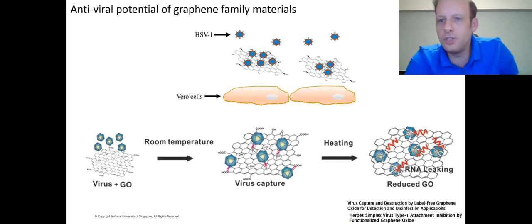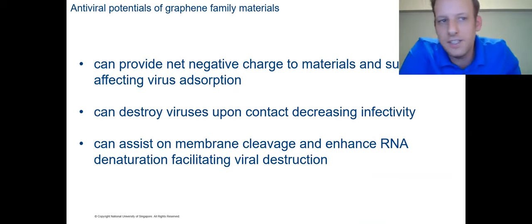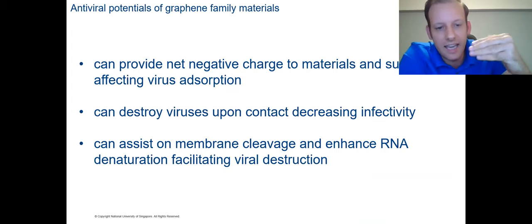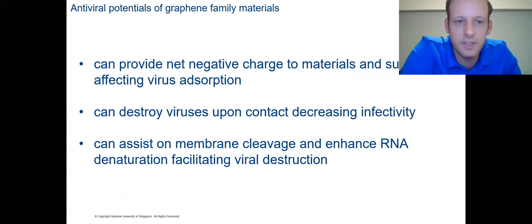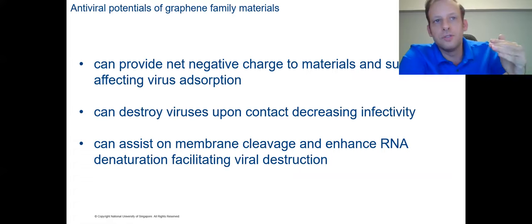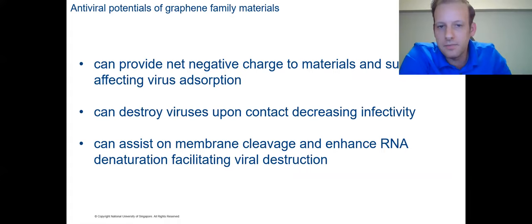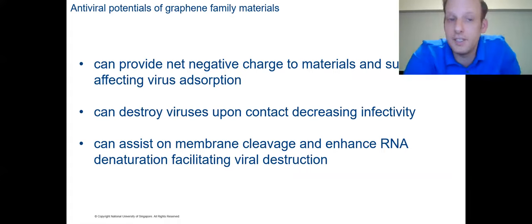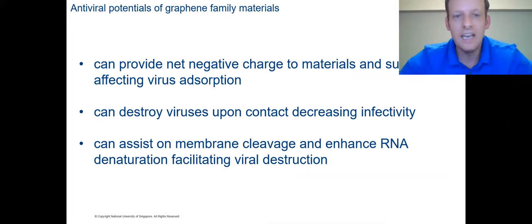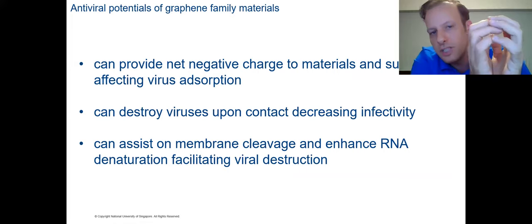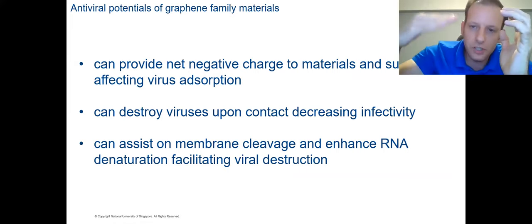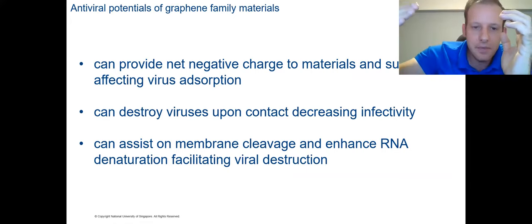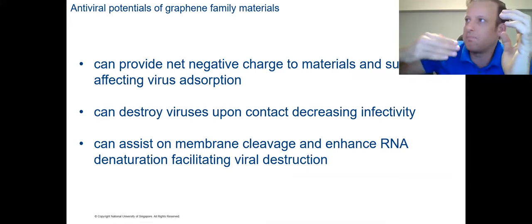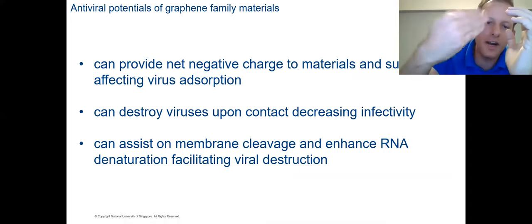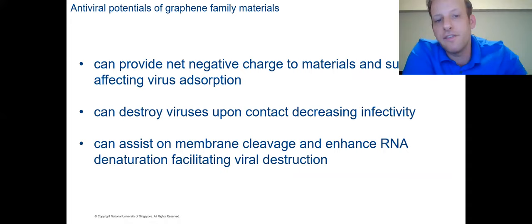summarized way, we could use graphene in at least 3 different ways to start fighting viruses. Either by changing the electrical charge of the materials, or you could destroy viruses by the sharp edges of graphene, for instance, or graphene oxide, or whatever graphene family material, or you could use graphene materials to bind to the virus, and then use other sources of energy, either light, UV, for instance, or plasma, or maybe heat, to break more and more, making it even easier to disinfect environments.